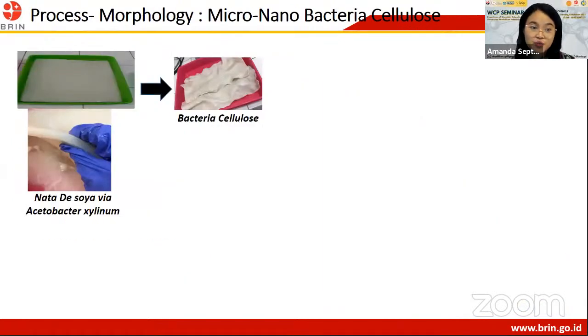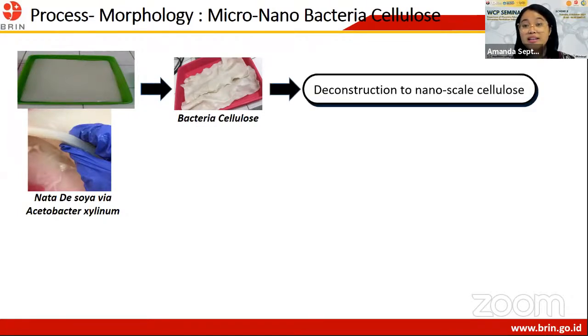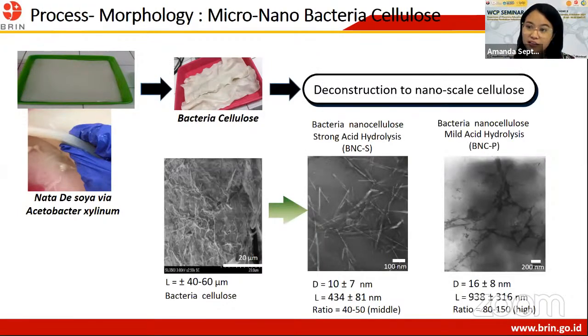So we have successfully produced nata de soya, and then transformed it to bacterial cellulose from this tofu liquid waste using the bacteria Acetobacter xylinum. And then after that, we do the deconstruction into nanocellulose. So here is the morphology of the cellulose. From here, you can see that from the micro size, we can transform it to nanocellulose.